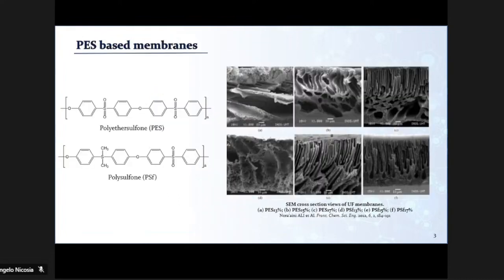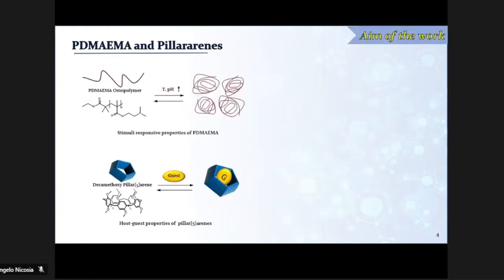The most common polymers employed for the preparation of such membranes are polyether sulfone and polysulfone. As you can see from the SEM images, they are characterized by very small pores, but they can be easily blended with functional nanofillers or polymers in order to increase their absorption performances as well as the selectivity of the membranes. With this in mind, we decided to study the effect of these two systems: poly(dimethylaminoethyl methacrylate), PDMAEMA, a polymer sensitive to stimuli such as pH and temperature, and pillararenes, which are macrocycles able to include different molecules in their cavity by host-guest interactions.